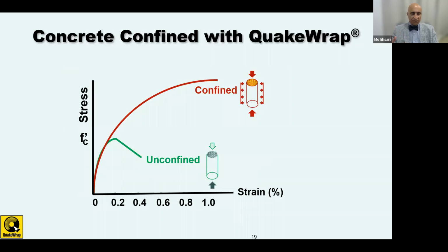So the solution to this, of course, is to confine them by wrapping them, whether with steel or with FRP material. If you wrap them, you not only increase the strength of the column, as I'm showing here with a concrete cylinder, but the same idea applies to a cylinder or a column. The unconfined one performs like this, but when you confine it, you not only increase the strength, you also increase the ductility or the strain at failure, which is a major benefit for seismic applications.